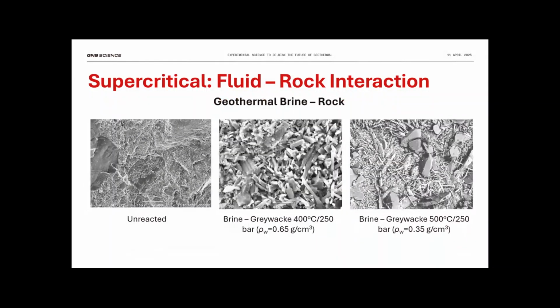If we put geothermal brine, so this is real geothermal brine from a power station in New Zealand. Again, this is the unreacted on the left. In the center, we have Greywacke reacted with brine, this time at 400, and we get an albite precipitate, mostly albite precipitating on the surface. And very interesting, at 500 degrees, 250 bars, we have quartz.